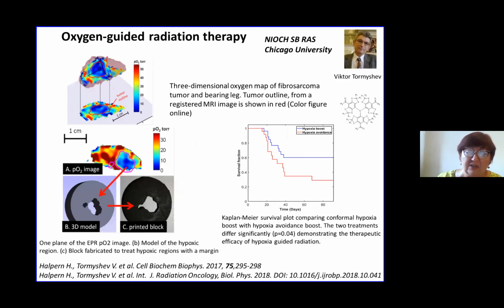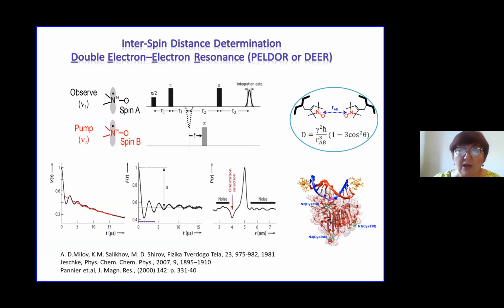Also another application, also together with our institute and the Chicago University, is oxygen guided radiation therapy. In this case, EPR tomography or Overhauser-induced tomography is made, and there are 3 images of the tumor and the concentration of oxygen is measured. And then one can make radiation therapy of only the region which has hypoxia, and the result is that one can use much smaller dose of radiation, and this is very good for health. So I think I convinced you that it is very good as a spin probe.